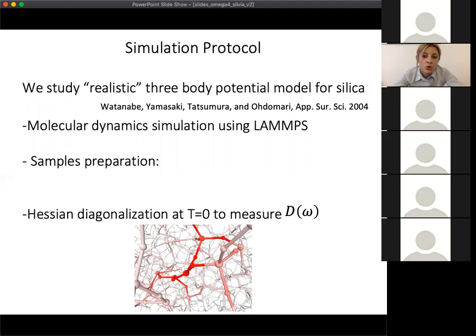One important note regarding this minimization is that we require that the force acting on each atom is less than 10^-10 eV over angstrom, so we want that our configurations are very well stable, very well minimized. After this we calculate the Hessian matrix for these configurations and we diagonalize them to get the eigenvalues and the eigenfrequencies and measure finally D(ω).